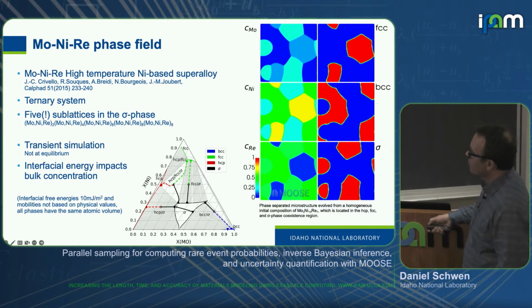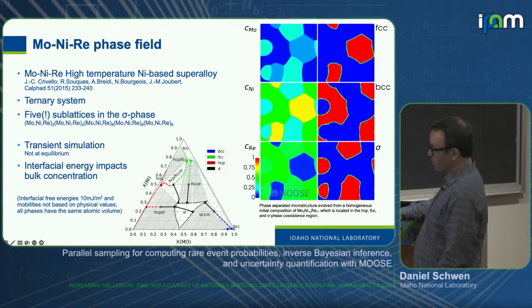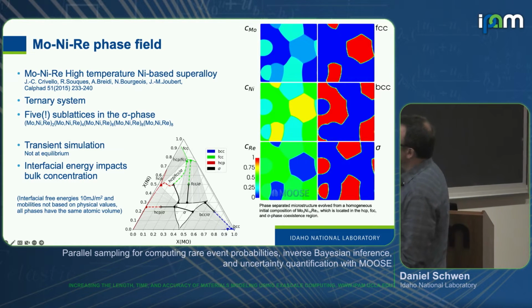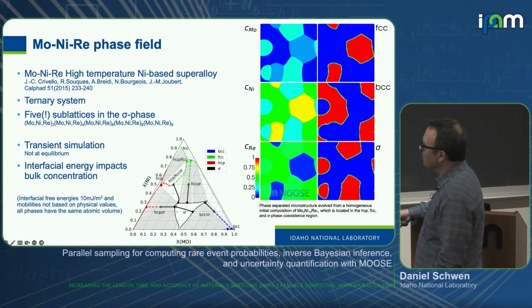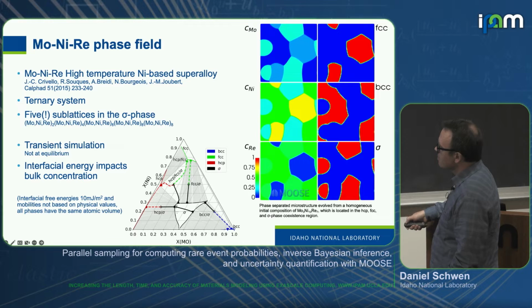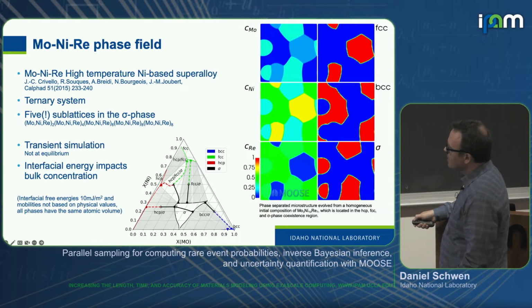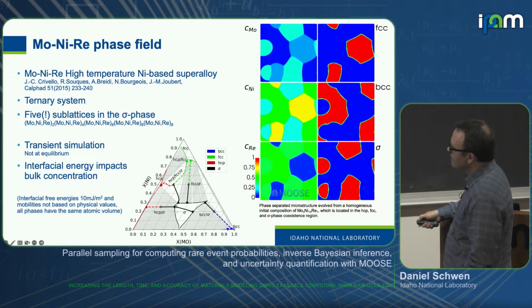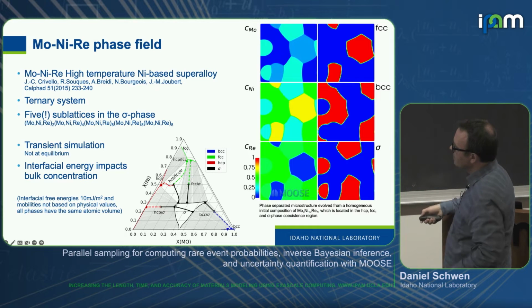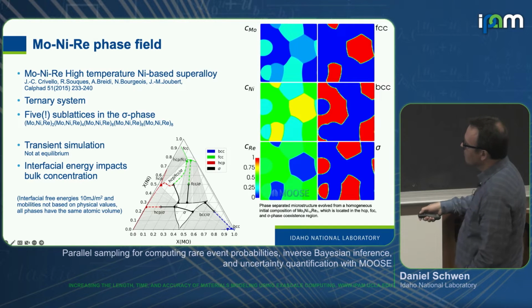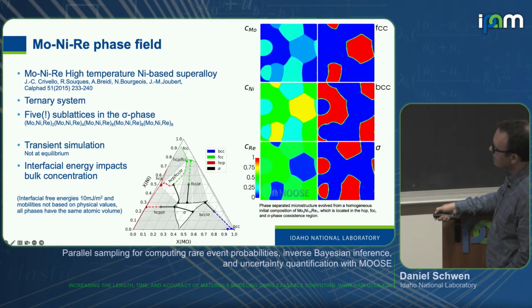Okay, and you can do that with more complicated systems as well. Molybdenum, nickel, rhenium, a high temperature nickel alloy that has 5 sublattices on the sigma phase. As a ternary phase diagram here, we can start a phase field simulation somewhere in an immiscibility gap, and those are the trajectories that the system takes as it phase separates, in this case into 3 phases, or here into 2 phases. So the symbols and the lines are taken from MOOSE simulations, whereas the underlying phase diagram is done with PyCalphad, and there's really good agreement. We really end up where we should on the phase diagram here.